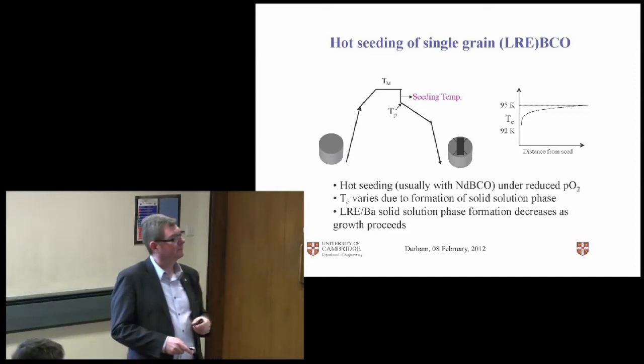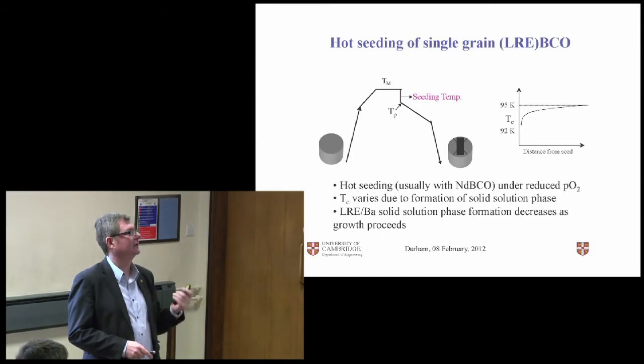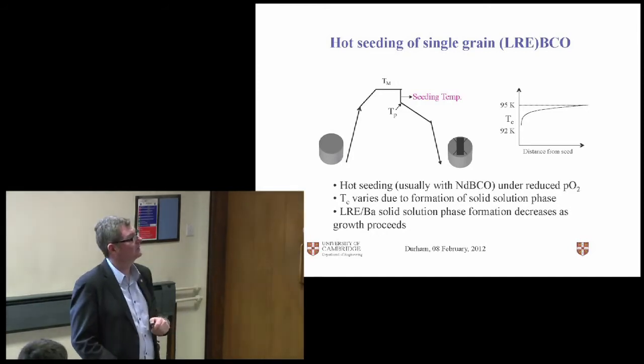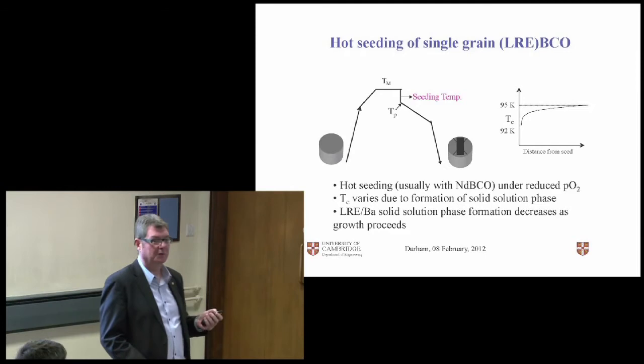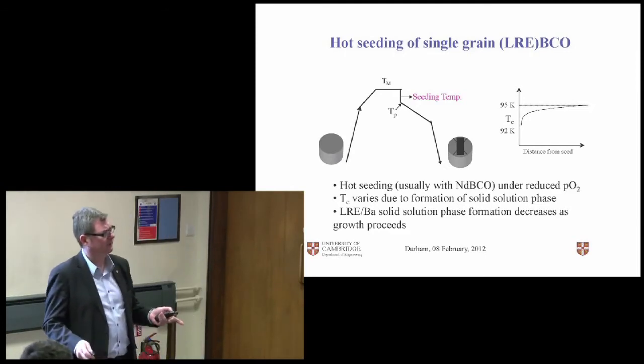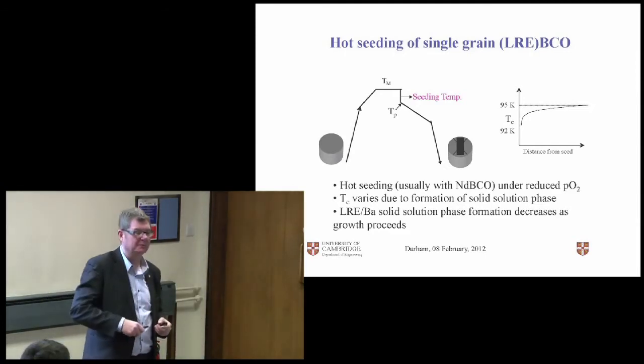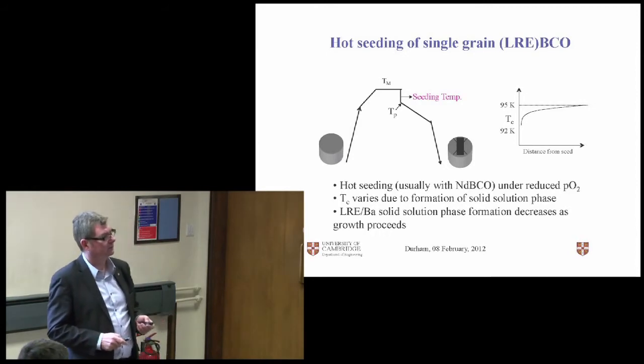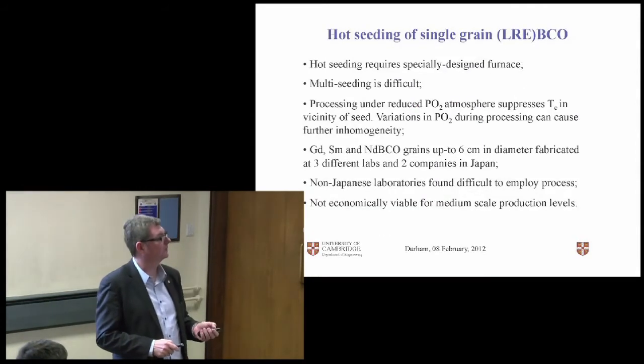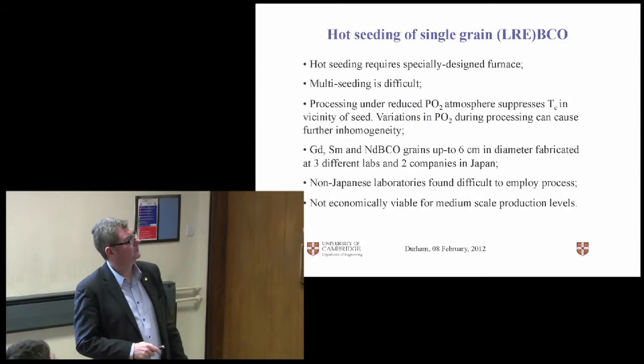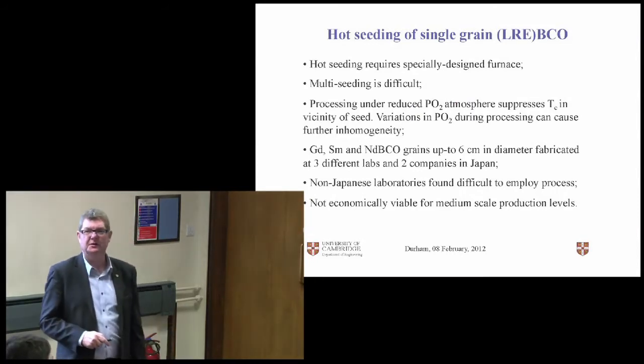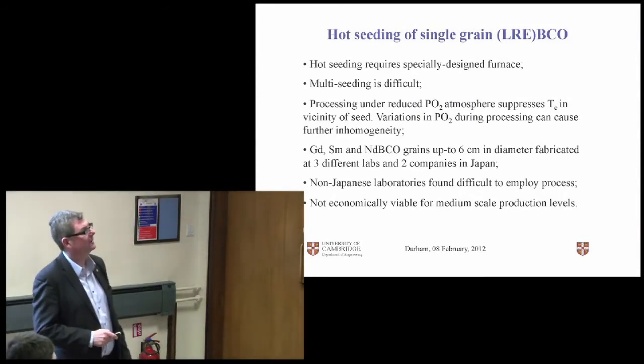Quite often, the Japanese quite rightly tend to publish the successes, but I was told it only works 1 in 20 times. They've developed a different technique where you seed from above now, but it's still a very difficult process to control. So in terms of hot seeding, you obviously require a specially designed furnace.